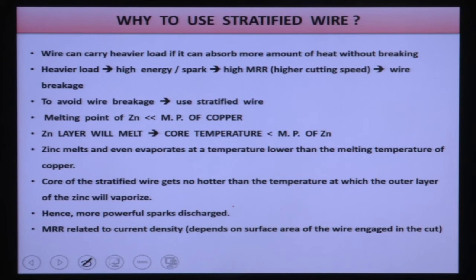A wire can carry a heavier load if it can absorb more heat without breaking. Heavier load means higher energy per spark, so higher material removal rate and higher cutting speed. If we give more current to the wire, obviously higher energy per spark will be generated, so the material removal rate will be high. But in that case, wire breakage will occur. To avoid that, this kind of stratified wire is used, where the core of the wire is copper, and outside there is a small layer of zinc or zinc alloy. The melting point of zinc is much lower than the melting point of copper.